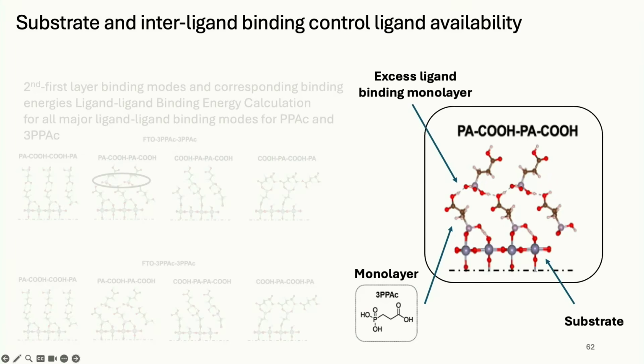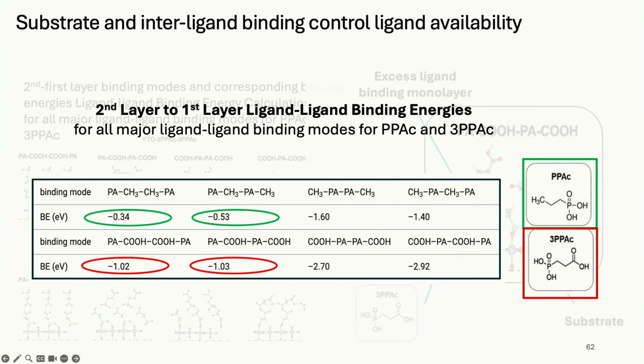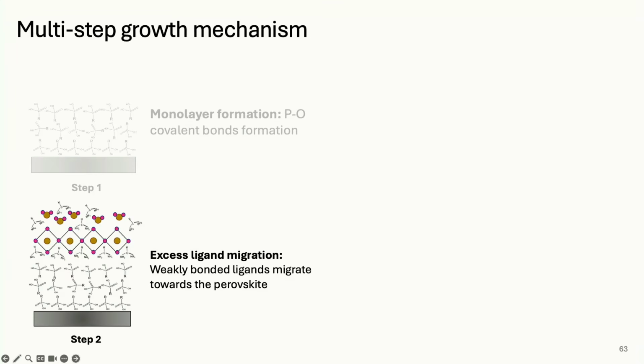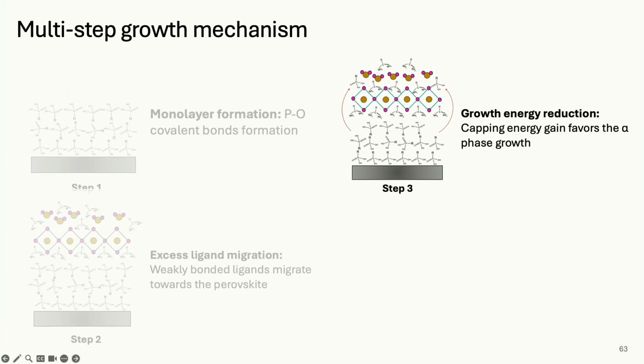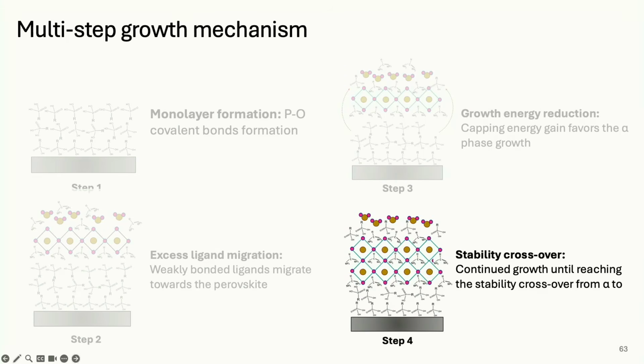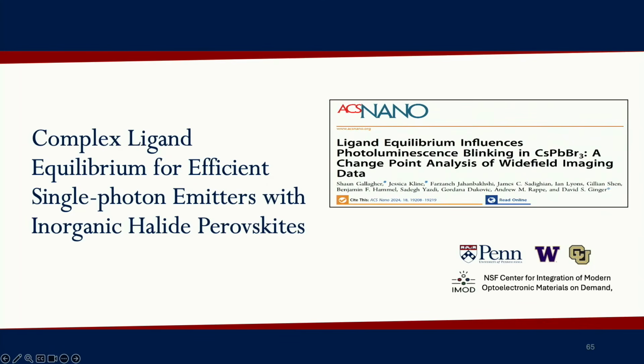I mean, it turns out it's a little more complicated than this. The actual mechanism is they deposit the phosphonic acid. This is our model. And so then the crystal starts to grow. But then these phosphonic acids get out of the way and diffuse to the top surface because they want to bond there too. And so you need to have enough phosphonic acid to kind of cap the top as well as the bottom. And so these phosphonic acids keep kind of migrating from the bottom up to the top to keep the material happy.